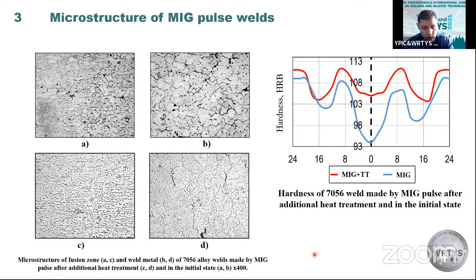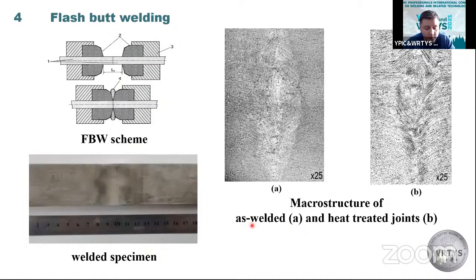One of the perspective ways to obtain sound joints with less heat treatment is welding in the cold state, such as flash butt welding technology. Using flash butt welding technology gives us good microstructure, but we have some issues with the heat treatment of this alloy. It was a T351 treatment, which was not only annealing but also a deformation state. So before welding, it was heat treated, and after that we obtained sound welded joints.